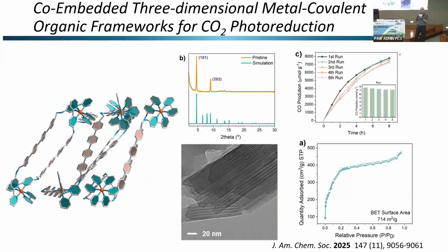If you can drive the reduction of a proton, well, what else can you do? Other things we've been doing with what we're calling metal covalent organic frameworks. It's not a MOF because our cobalt complex is covalently included in the structure here. You can see very nice periodicity, quite good internal BET surface here. So it's definitely a lot of internal porosity.